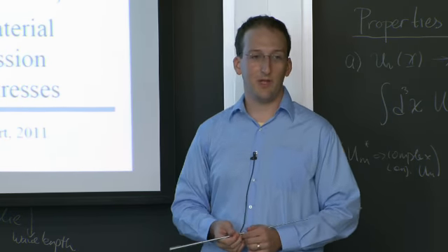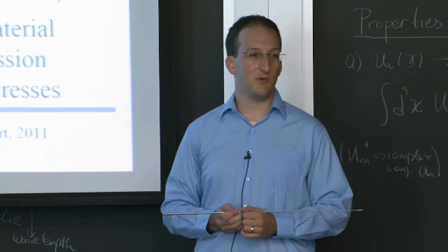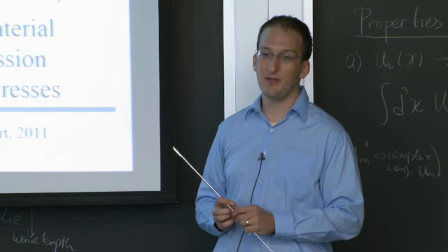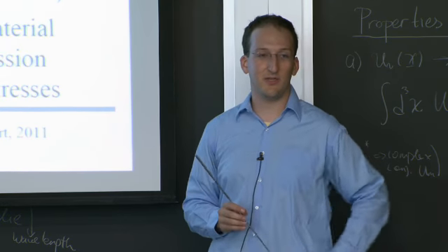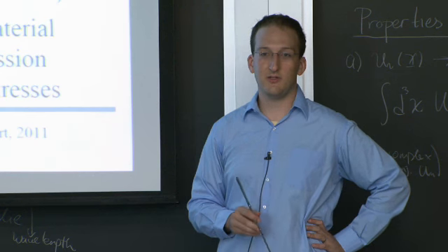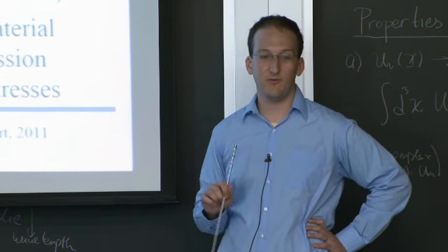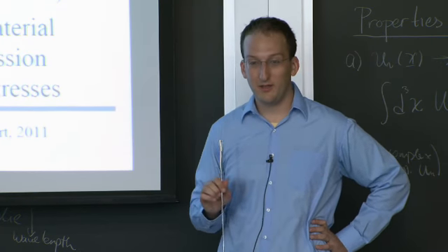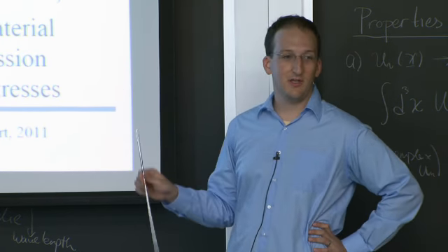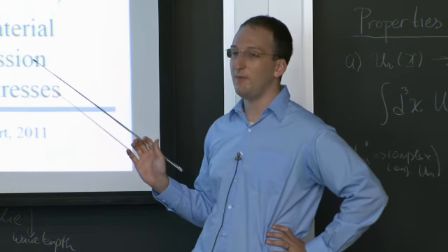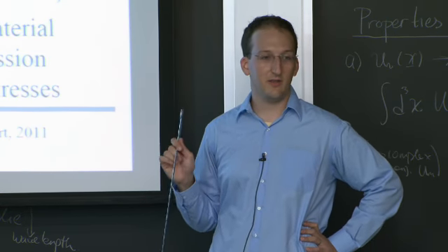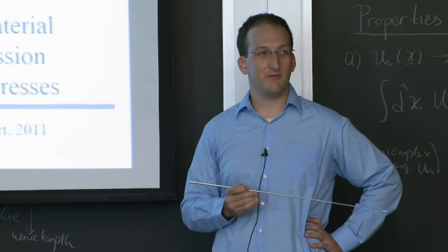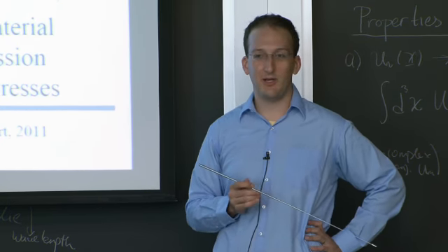For example, when uranium undergoes fission, it produces most of the elements. Some of these actually attack silicon carbide. Palladium in particular is one that I studied for my UROP. It turns out palladium can attack silicon carbide and form intermetallic phases, which are either brittle or liquid at pebble bed temperatures. They're thinking of using zirconium carbide as an alternative, and the testing that we've done shows that it fares up pretty well. But we haven't been able to find 100% dense zirconium carbide anywhere.